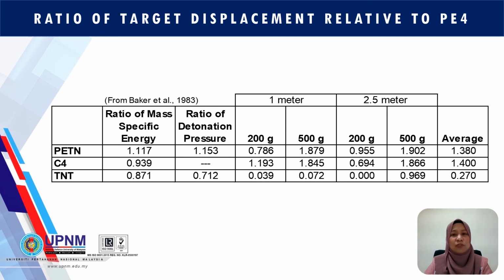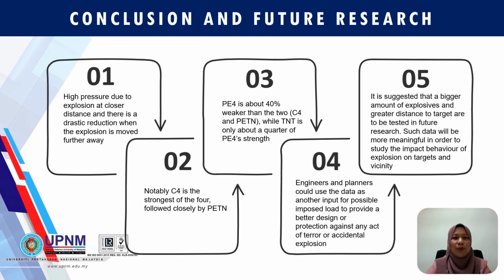So for conclusion, we can say that from the experiment that we have conducted, we found that C4 is the strongest of the 4, followed closely by PETN. PE4 is about 40% weaker than the two, C4 and PETN, while TNT is only about a quarter of PE4 strength. So it means that from the experiment that we have done, C4 is the strongest one, followed by PETN, and then PE4, and the last one is TNT.